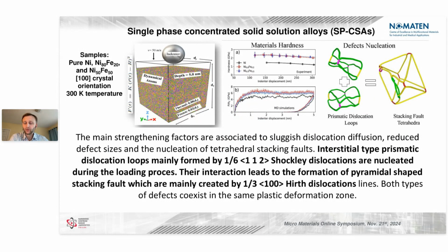We wanted to understand what is happening within the nickel-iron system, as this is a model. These are two basic elements from which high entropy alloys with FCC structure are built. In this case, we noticed that when we increase the amount of iron in the material, we observe hardening. And we checked with transmission electron microscopy, and we observed that there are stacking fault tetrahedra created when we deform the material. However, we didn't know how they are being created. What is the road towards creation of those features? By exchanging information with the numerical team, we came to the conclusion that these are basically prismatic dislocation loops, and their interaction leads to the creation of those features.